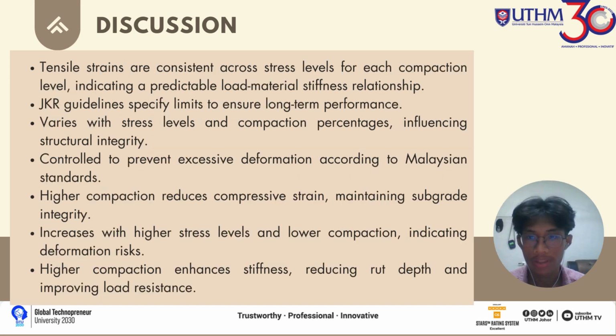Discussion for Figure 4: values are consistent across stress levels for each compaction level, indicating a predictable load-material stiffness relationship. JKR guidelines specify limits to ensure long-term performance, which vary with stress levels and compaction percentage, influencing structural integrity, to prevent excessive deformation according to Malaysian standards. Higher compaction reduces compressive strain, maintaining subgrade integrity, which increases with higher stress levels, while lower compaction indicates deformation risk. Higher compaction enhances stiffness, reducing rut depth, and improving load resistance.